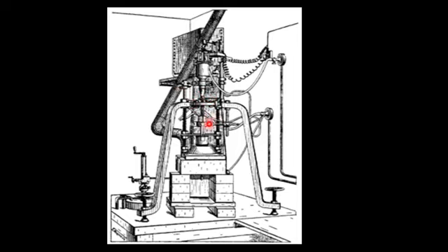Okay, so the oxyhydrogen flame interacts somewhere here with the material in powder form. The oxyhydrogen flame, which operates at high temperature around 2000 degrees centigrade, melts the precursor material which we want to fabricate as a synthetic gem. Then the precursor material in the form of melt is transported onto the surface of the substrate, which is located on the stand of this instrument.